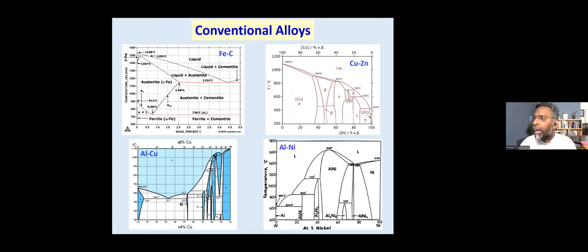As a result, most of the conventional alloys have been majorly used on one end of the phase diagram, and people hesitated to go to the center of the phase diagram. The moment you go to the center, that means when I have 50% of element A and 50% of element B, such alloys typically have intermetallic compounds, and a number of compounds in these phase diagrams that you can usually see at the center. As a result, such compounds being brittle, people avoided going to the center of the phase diagram.